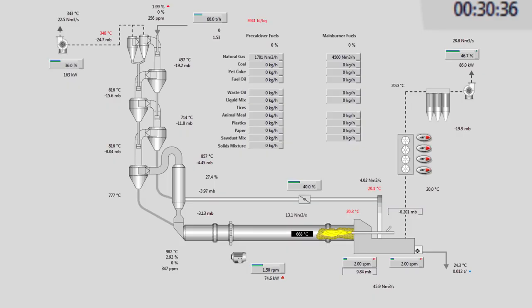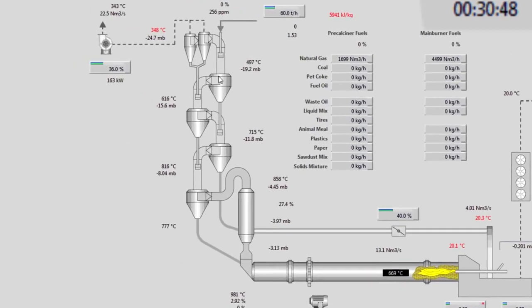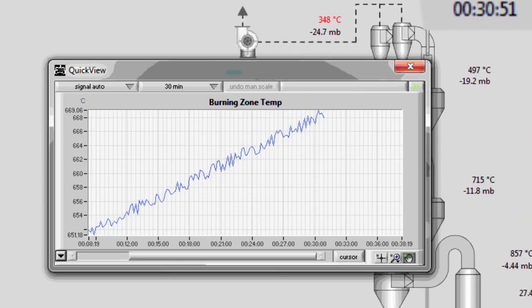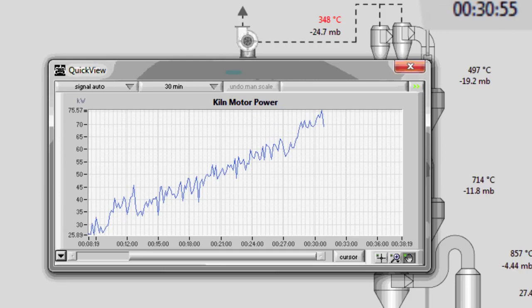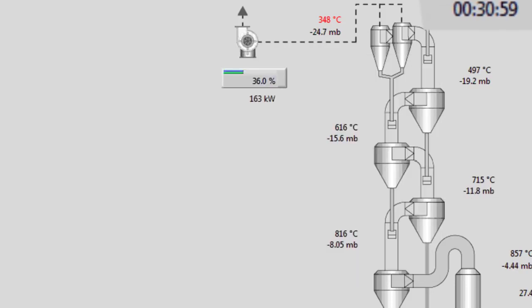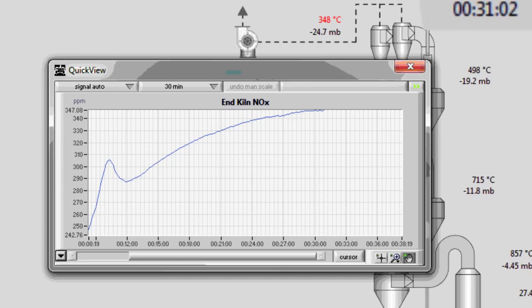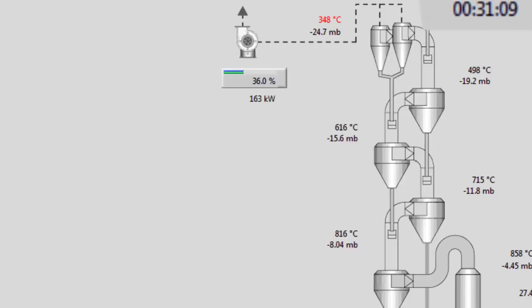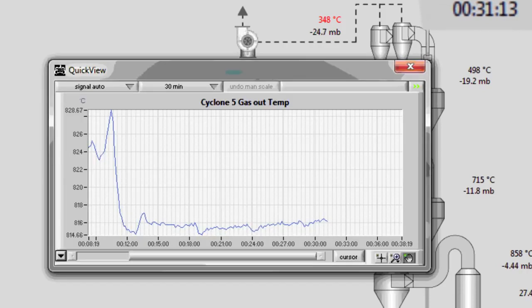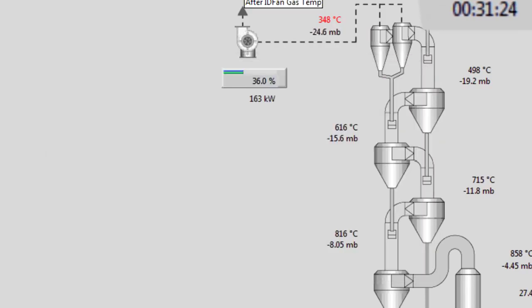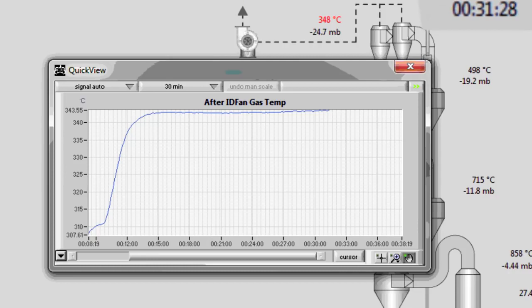After 30 minutes of feeding, notice the operation time will be displayed on the system. Still no material detected in the burning zone, BZ. O2 levels are nice and low, no CO. Burning zone temperature increasing slowly, kiln drive power increasing, kiln inlet NOx increasing, stage 5 temperature very nice and stable. Temperature at ID fan hot but stable.